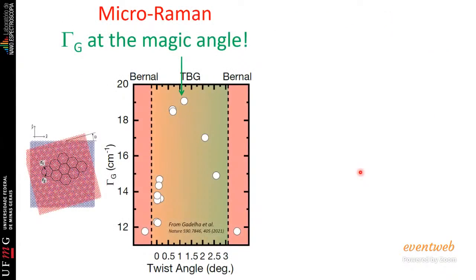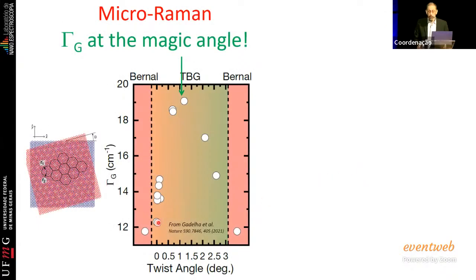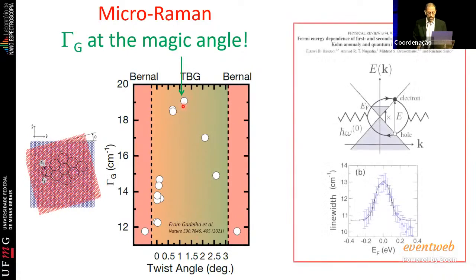All right, and finally, going back to the magic angle problem here, what we are imaging here is the width of this peak by changing the twist angle from 0 to 3. Okay, so at the very small angles, we see that the width is maximal at the magic angle. So why is it? Of course, it must have to do with something like this, but now you are tuning the width, not with gating, you are tuning the width with the rotation.